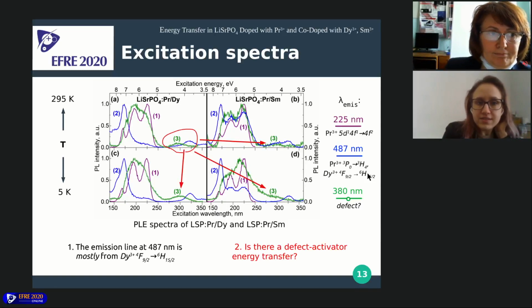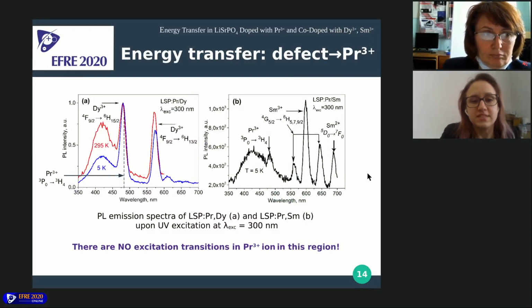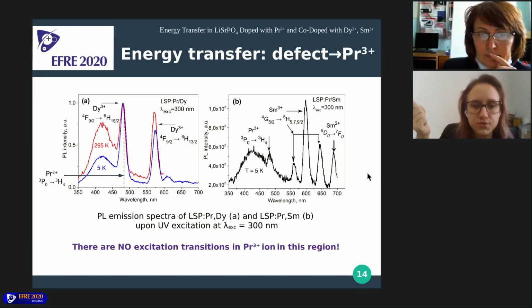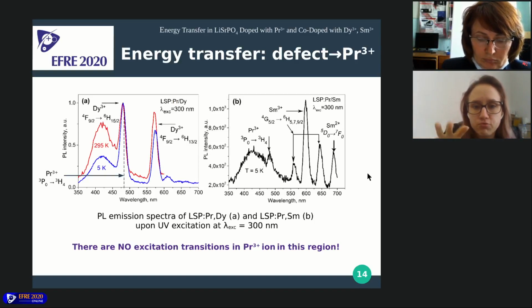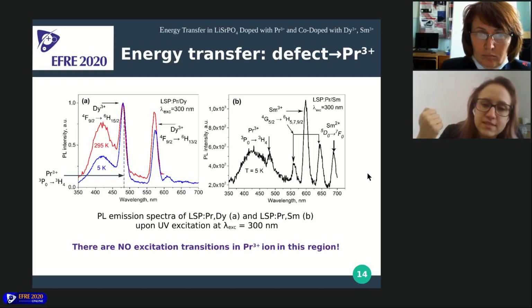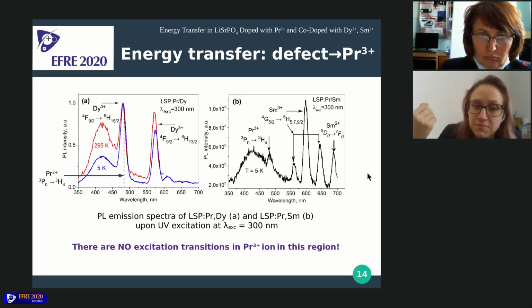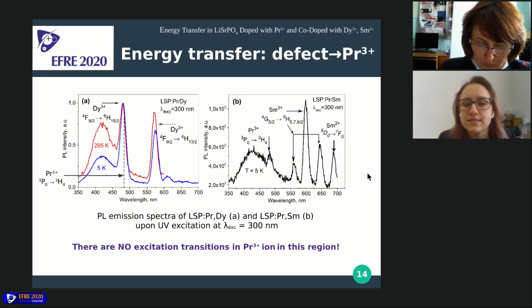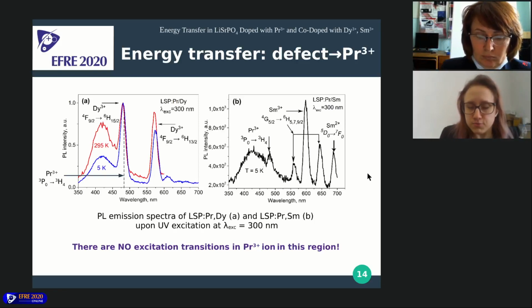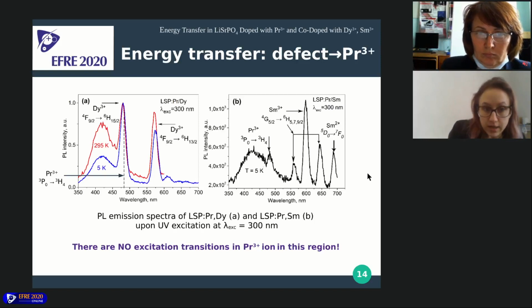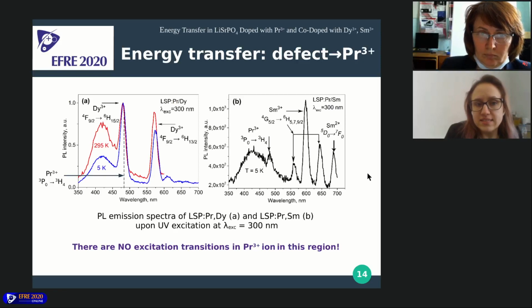And it probably indicates that there is also energy transfer between this presumable defect and activators. In order to verify that, we studied emission spectra under this excitation, and indeed, we can see that this defect emission is intensively excited, and there are also emission lines of these activator ions, which proves our assumption. And another interesting thing is that on the right side, emission spectra for the samarium doped sample, there are also lines that can be assigned to divalent samarium, which weren't seen under host absorption excitation nor praseodymium direct excitation. So it proves that this defect influence should be studied in more detail.